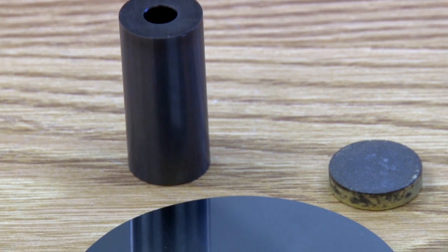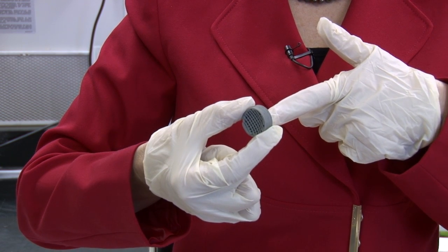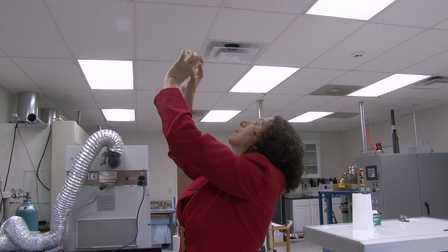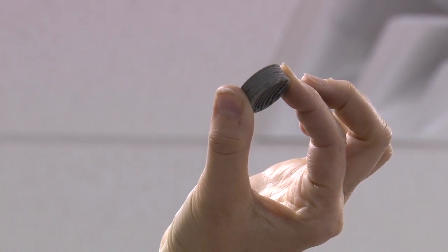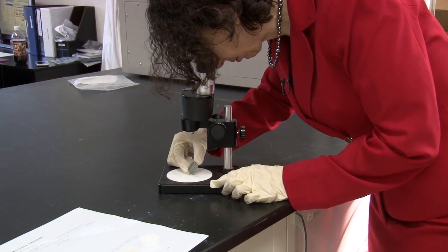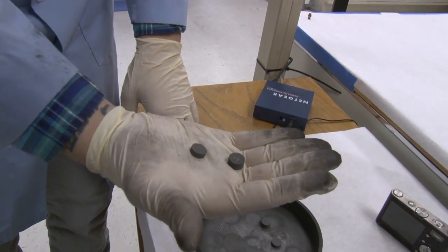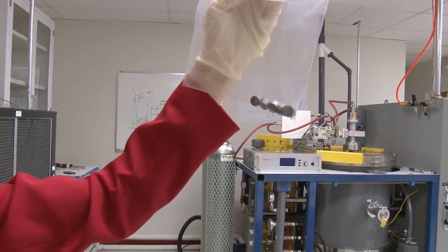The goal is to make the industrial manufacture of high-quality UHT ceramic parts faster and cheaper. Take this silicon carbide filter designed to strain molten metal — it gets extruded in an additive manufacturing process called Robocast, then fired in Ceralink's UHT Microwave Assist furnace. It's like squeezed out of a tube of toothpaste or Play-Doh, and it builds up a part in three dimensions. The firing, by using our type of technology, is much faster. Faster, cost-effective methods to bring ultra-high temperature ceramics to the marketplace — it's an idea that's heating up.